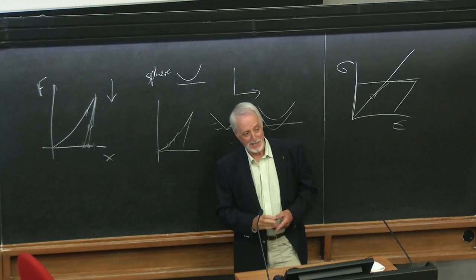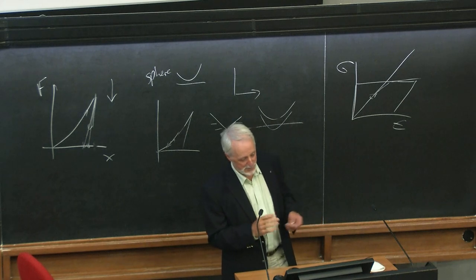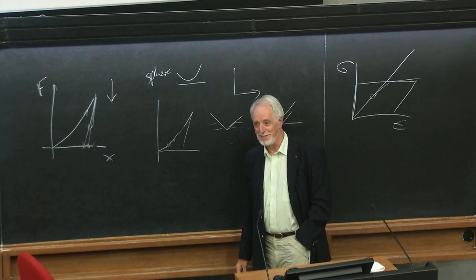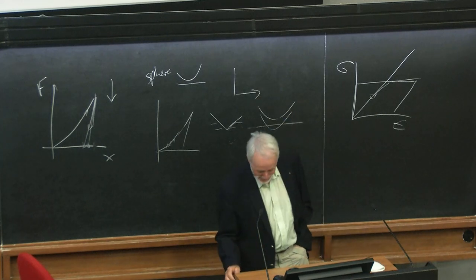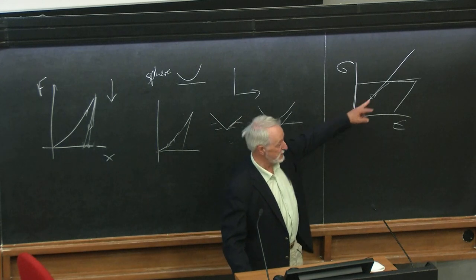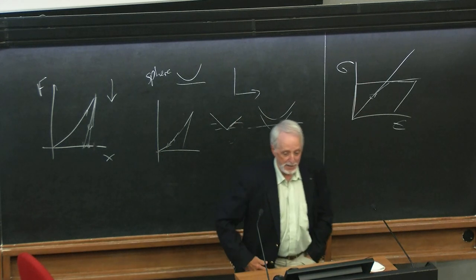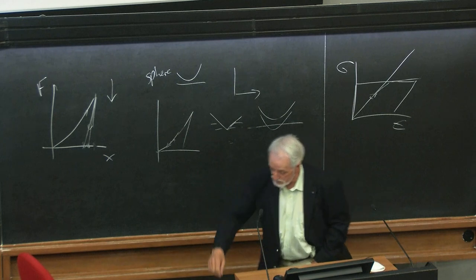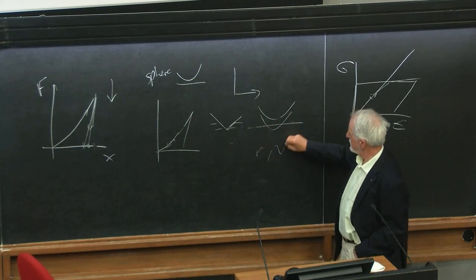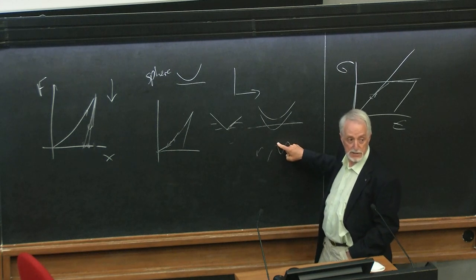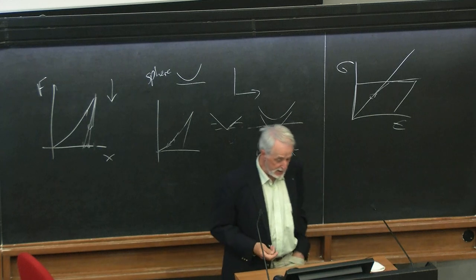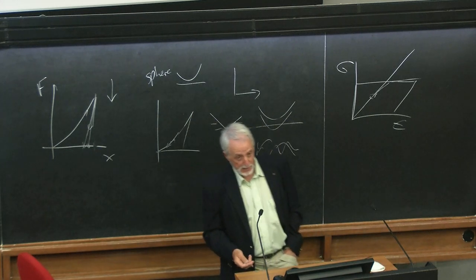Now, at this point, I'd be saying, hey, great, sorted. But one of the troubles with making a new piece of apparatus is that you push it a little bit further and you discover, oh dear, it doesn't seem to quite work as you expected. And of course, you look at that, you can't really expect it to work perfectly because we know reality contains elasticity. So if you do this now instead of a sharp tip, but instead of that, something which is round, where we know the elastic terms matter, they matter here, but they're not variable scale. Here, they're even more important. And what we find is actually you don't get this nice behavior.